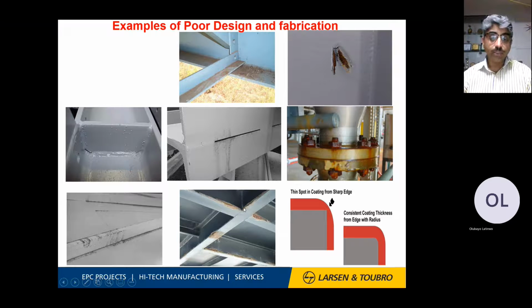Same way for the corner joints, as I said, it is prone to early corrosion because of the reasons as shown here. If we apply the paint on the very sharp corner, it's not going to stick much paint over that corner. And because of that, it is going to give you premature failure like this, as shown. So what do you want to do? You just make certain tapers, 3 degree, so that the edge gets a radius, and because of that, the DFT, the dry film thickness, is more as compared to the traditional one, and you get a better life of the component.